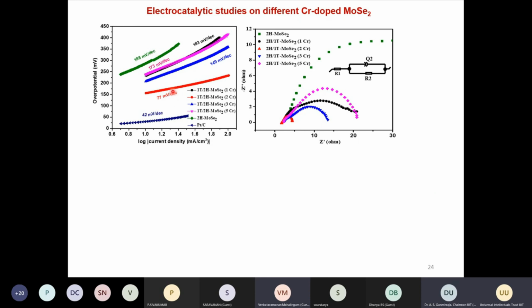So this is for the 2% doped chromium sample, which is also supported by the impedance measurements. What we do in impedance measurement gives an idea about the solution resistance as well as the charge transfer characteristics of the material. What we can see is that the hump, which is the semicircle, is very small for the 2% doped chromium, which shows that the resistance is very low in this sample, for conductivity for the electron to reach, or the OH minus or H plus to reach the electrode, compared to other samples.